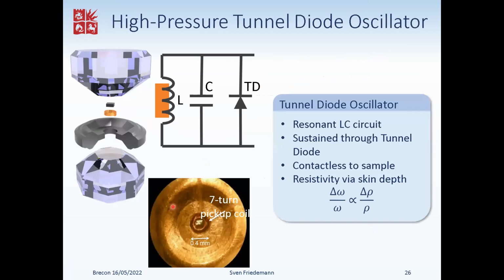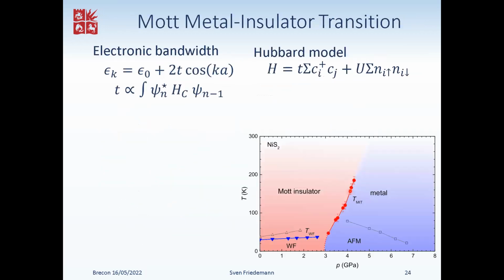Just so I could see the phase diagram one more time. So where are we in the phase diagram? Of course, we are here on the metallic side. In order to observe quantum oscillations, they are only present here. And that magnetism is the non-collinear one, yes. Okay. And is there any resemblance, just out of curiosity, between the magnetism on the other side? I don't know off the top of my head, to be honest. You would expect they don't have to have anything in common. The zero pressure magnetization definitely shows some weak ferromagnetic hysteresis, so in that sense it is already different, but I'm not sure whether there's above it an antiferromagnetic state with the same structure as in the metallic phase. I would have to look it up.